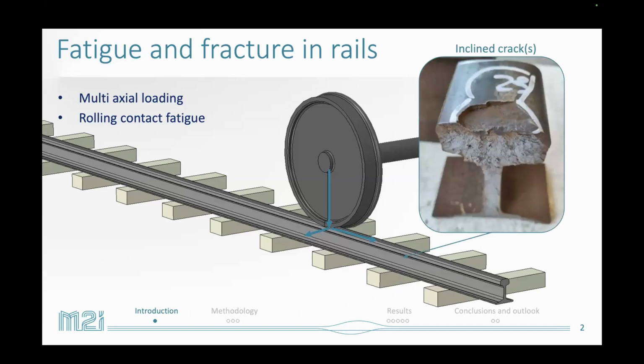And on the top left figure, you see an example from practice. So this crack on top is a so-called squat defect, which is an inclined crack from the head of the rail. And this vertical fracture surface was done in the lab, where the rail was fractured to be able to see the fatigue crack from practice.